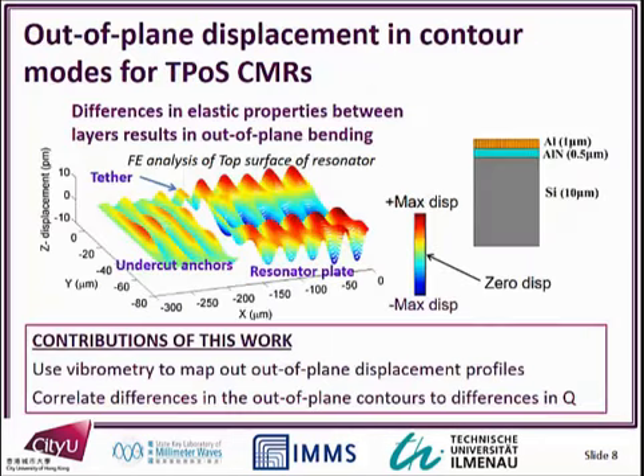And so, a closer look at TPoS resonators. Although the mode is generally lateral, if you actually do an FE analysis of it, you do see that there are these kinds of waves that go in the out-of-plane direction. What happens is that now, instead of having pure aluminum nitride, you've also got this heterogeneous stack of materials, and this mismatch, this difference in the elastic properties, would generate more out-of-plane bending. So we thought, why not use this method to see what's actually going on?